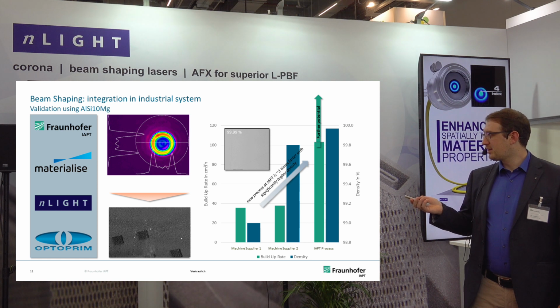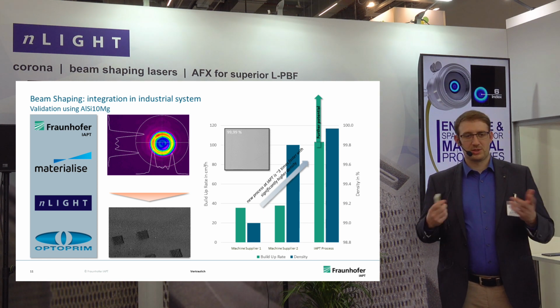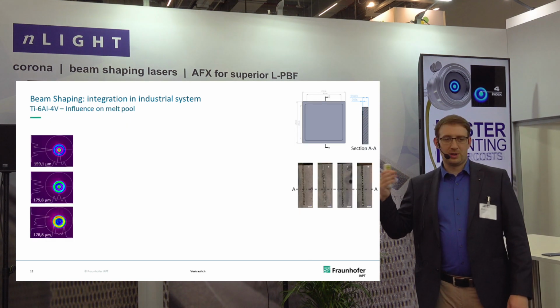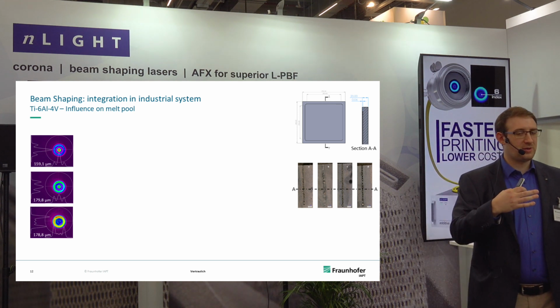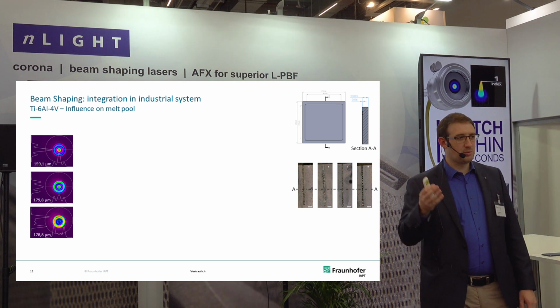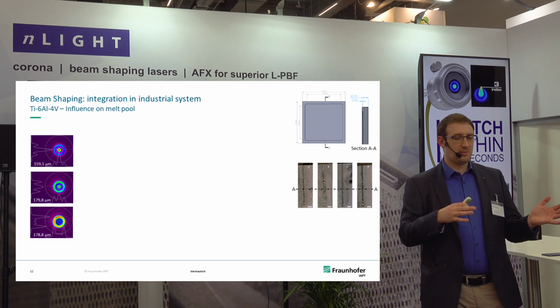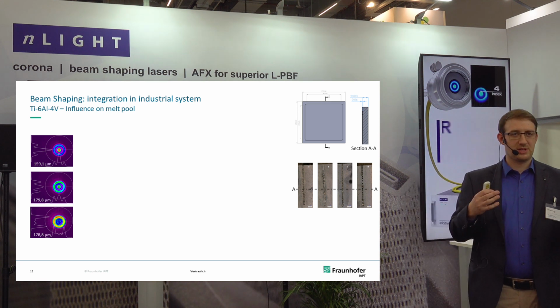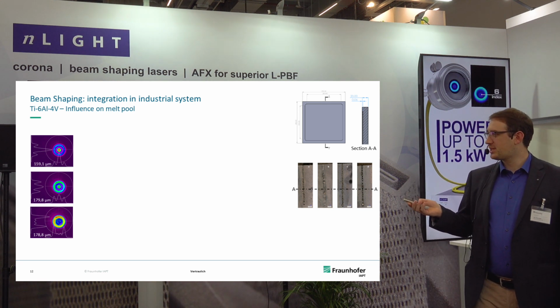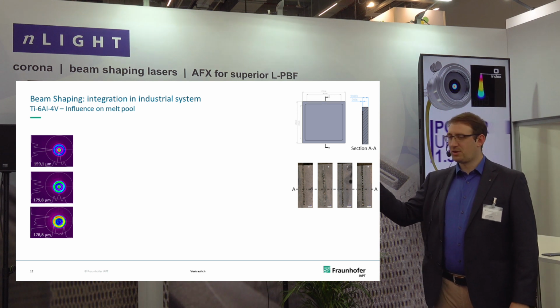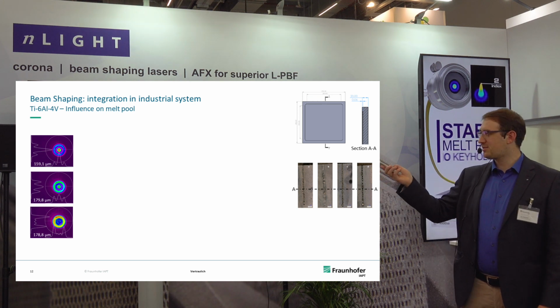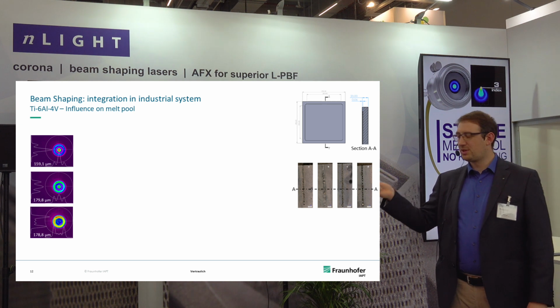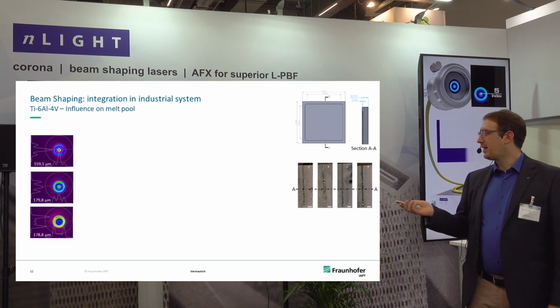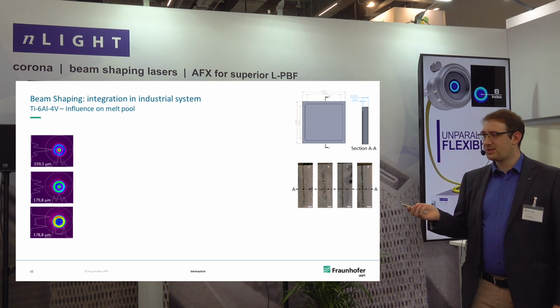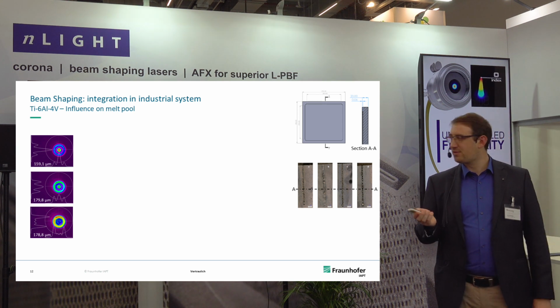So then we looked into another material, titanium. We wanted to know how the beam profiles influence the melt pool behavior. In the beginning I showed some cross-sections of single weld tracks. We did this for titanium as well. If you're familiar with the nLIGHT laser, it's index 4 at the top, 5 in the middle, and 6 at the bottom, for different combinations of laser power and scan speed.